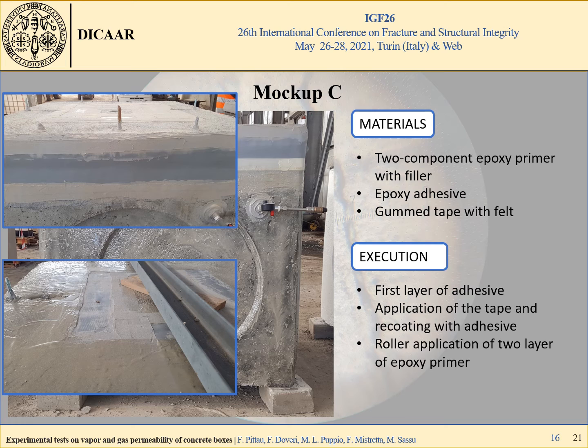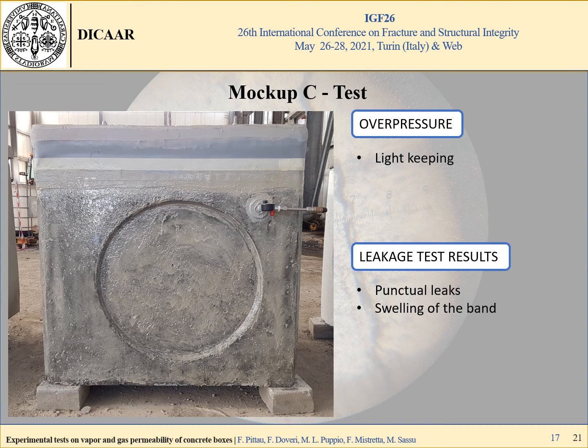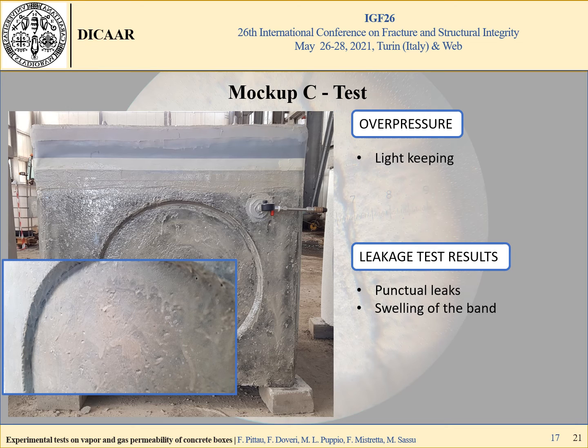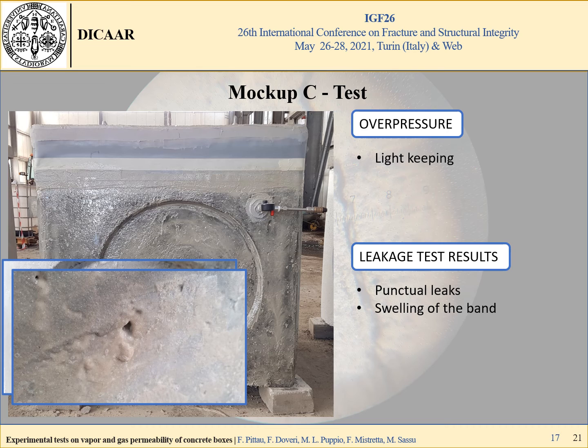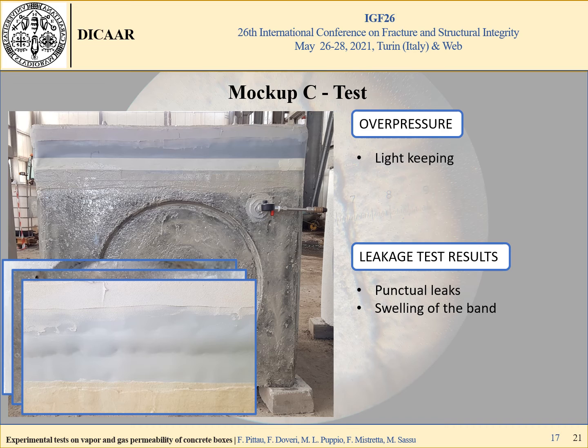After fixing, the primer was applied with a roller, but it can also be applied with normal compressed air or brush. During the test, we had a very slight overpressure, disturbed by the presence of punctual leaks. The losses were attributed to the surface roughness and the difficulty of applying the coating on it. The strip was too deformable, and there was a swelling; the test was interrupted due to the fear that the strip would come off. But it was a very difficult situation for the strip. In reality, we will never have a case of discontinuity in a tank.